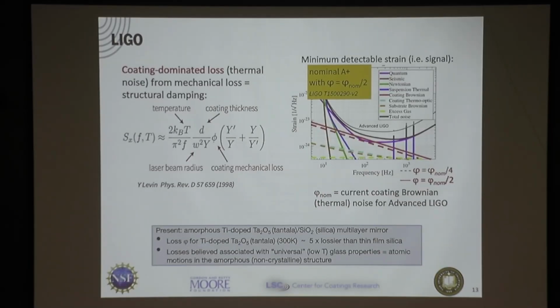You're averaging over it. This is much like the argument if I take a string. You've all done experiments where you propagate waves along a string. That string is not some single crystal. It doesn't matter. Sound waves propagate quite happily in non-crystalline materials. So it was believed that when you cool down an amorphous material, it should have a T-cubed law. So there was quite a bit of surprise when it didn't. There is a T-cubed dependence, but there is a linear T dependence also. And it is very hard to figure out why there is a linear T dependence to the heat capacity.